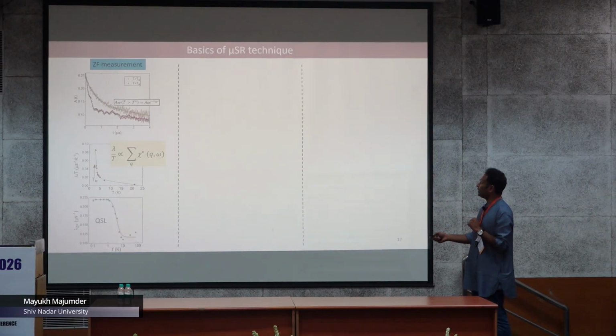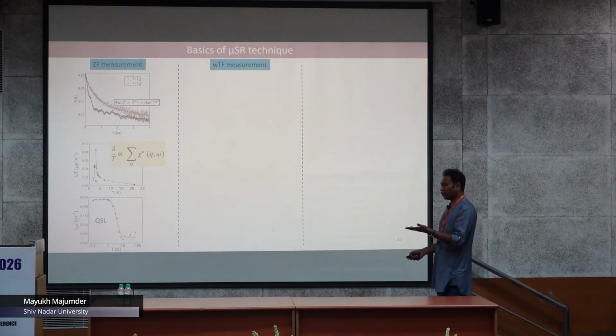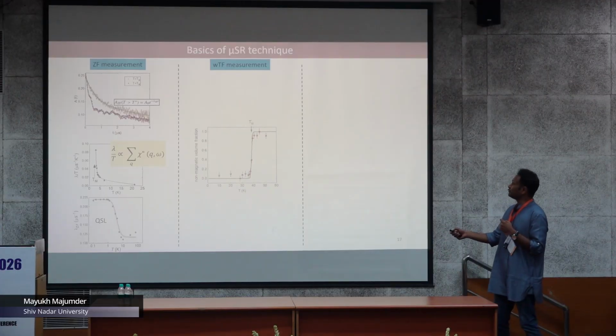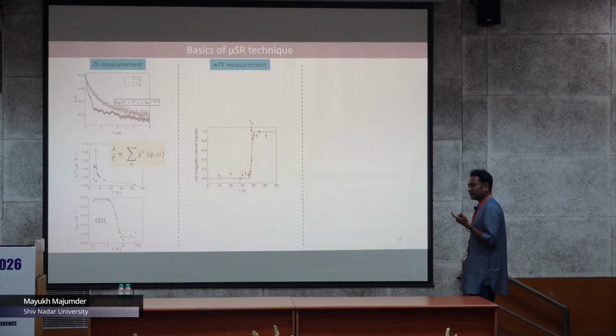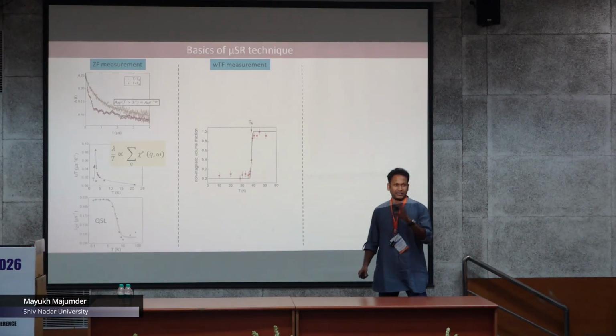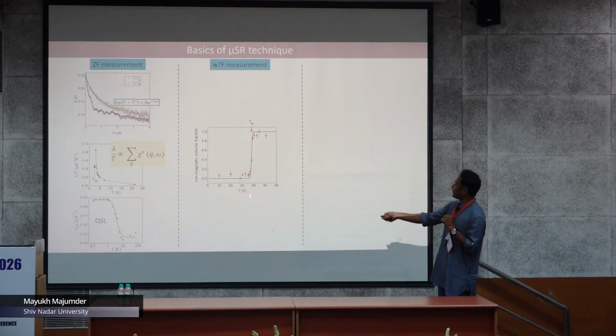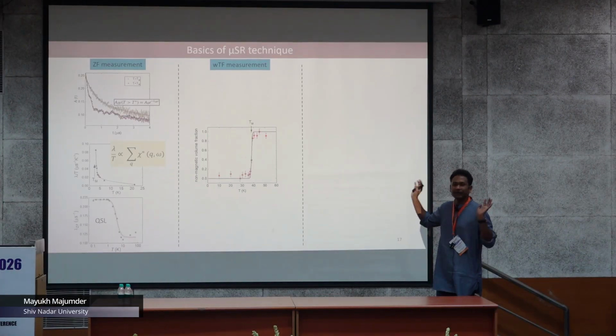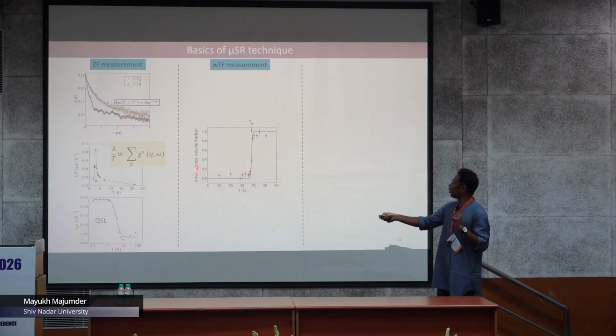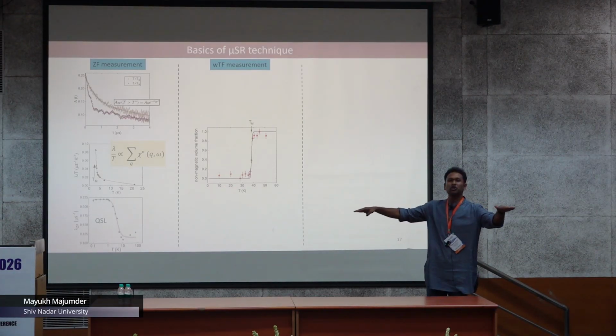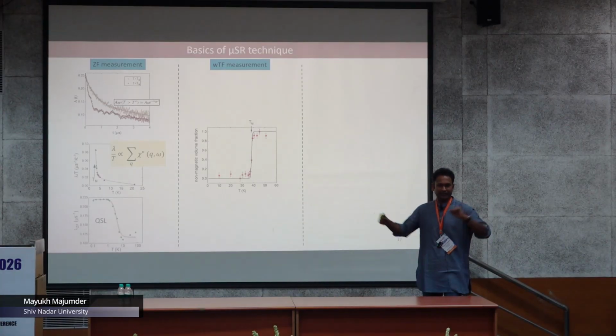This is the zero field one. Weak transverse field is also one protocol, which gives you information about the temperature dependence of the non-magnetic volume fraction. As for example, if you have an ordering, let's say around 40 Kelvin, you can easily expect that in the paramagnetic state you have 100% of the spins which are non-magnetic, right? And in the ordered state you would be expecting there are 0 spins which are non-magnetic, right?